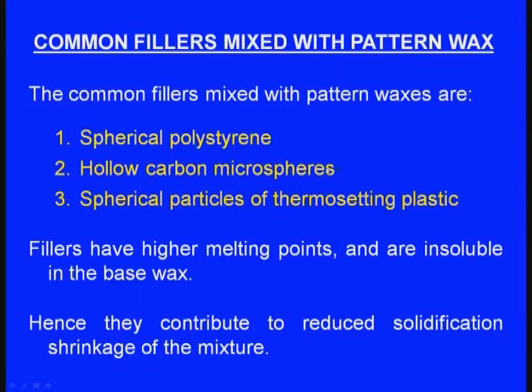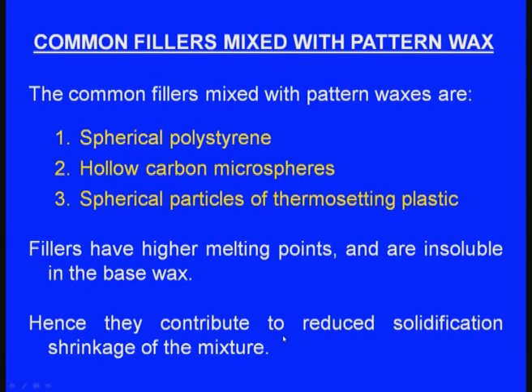When liquid wax is injected into the metallic dies and solidifies, a shrinkage cavity can sometimes arise, making that wax pattern unusable. By adding fillers, shrinkage is reduced. Generally two or three waxes are mixed in certain proportions along with fillers so that the blend develops the required fluidity, required hardness, and minimum shrinkage. Friends, we will continue this in the next lecture.